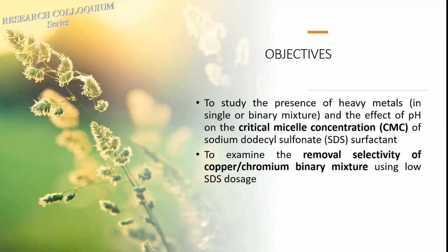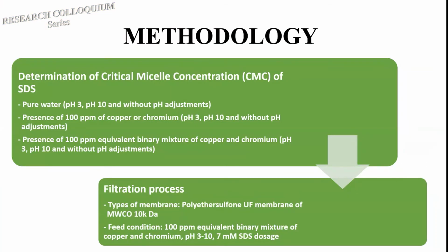So basically, the work is designed with the purpose to study the presence of the heavy metals, either in single or binary mixture, and the effect of pH on the critical micelle concentration of SDS. Later I will explain again what the so-called critical micelle concentration is. After this, I am also going to examine the removal selectivity of a copper-chromium binary mixture using a low SDS dosage. So basically, this work can be split into 2 major sections. The first major section is